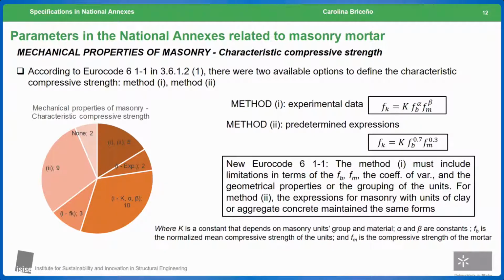The second method is based on the use of predetermined expressions, as the one shown here in this case for general purpose mortar. We see that the constants alpha and beta have been replaced by the values of 0.7 and 0.3 respectively, as well as in the case of K, whose values are available in the standard. In the case of the 2018 version, method one includes limitations in terms of the compressive strength of the unit and of the mortar, as well as the coefficient of variation, and the geometrical properties or the grouping of the units.